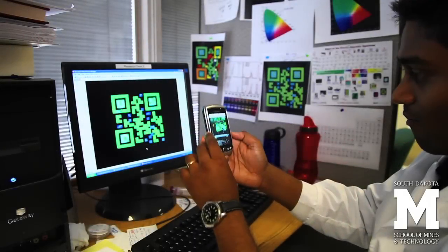The IR is converted into visible light at 530 nanometers wavelength by these upconverting nanoparticles. We use a camera with an IR cutoff lens fixture because cameras usually pick up the IR, not the upconversion. So with that IR cutoff lens attached, the camera just sees the QR code.